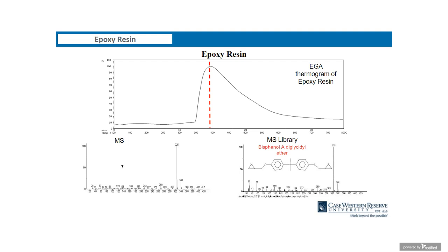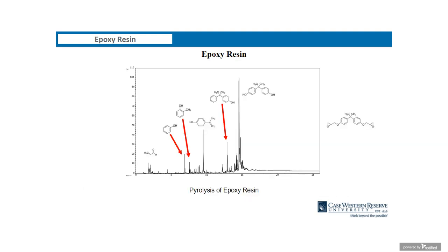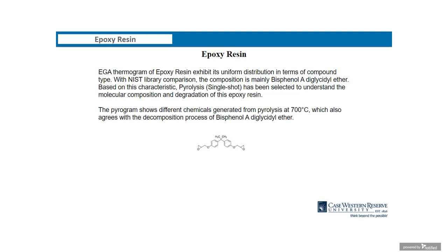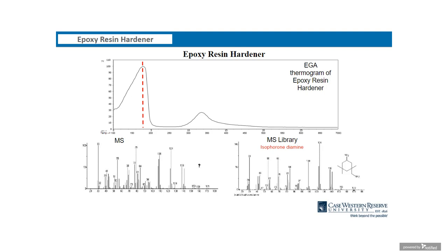You can see that the application of EGA, evolved gas analysis, allowed us to look at the composition of epoxy at a range of temperature. What this tells us is that we don't have low volatile components on epoxy. The library spectra confirmed the major presence of bisphenol A. So this is a typical epoxy resin, bisphenol A, and actually without further going into the double shot and single shot, we did classify the presence actually of some esters or polyesters in this component, which was found in the higher temperature range here. But here you can see, based on the pyrolysis of the epoxy resin, the major components that we would attribute to the bisphenol A composition. And then the hardener is a typical amine composition. This isophorone diamine was confirmed by the mass spec library.